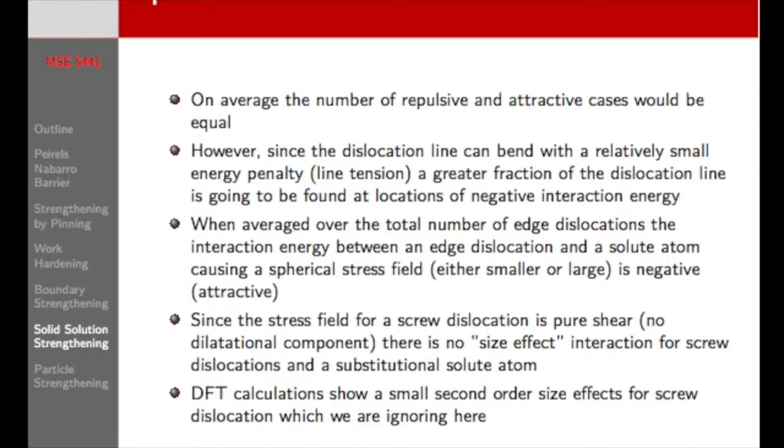Almost never, because dislocations are in a loop, and if the Burgers vector has to be the same for that entire loop, there are only 2 exact points on that dislocation loop that have no screw component. And as soon as you break into partials, you don't have a perfect screw component.